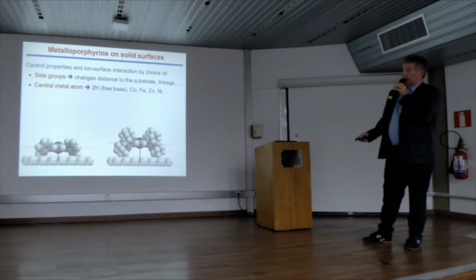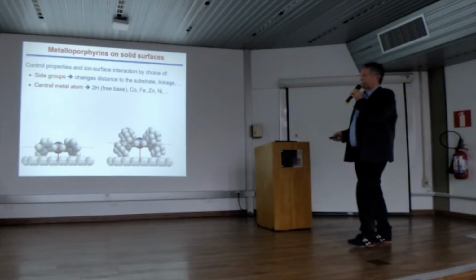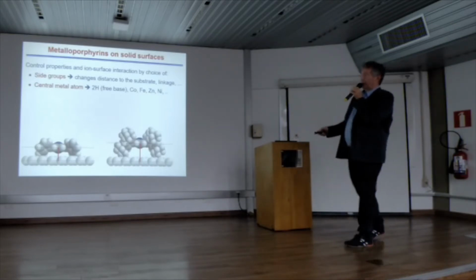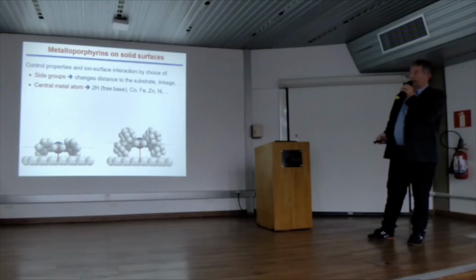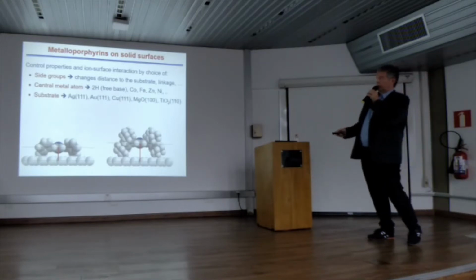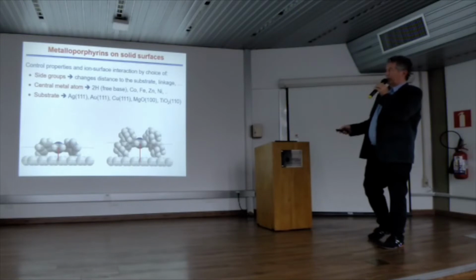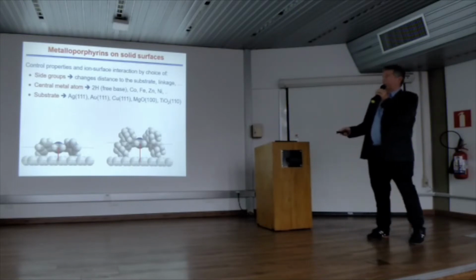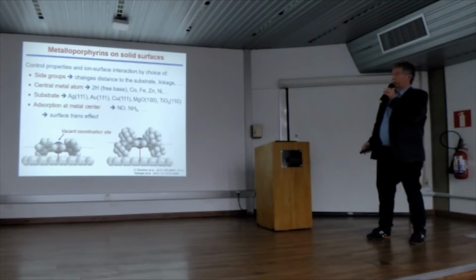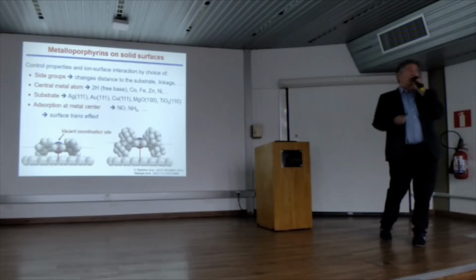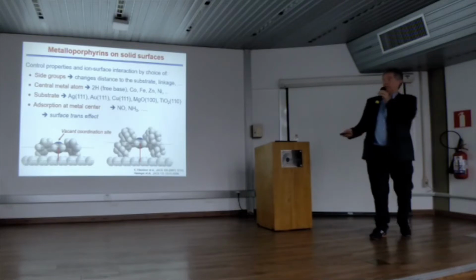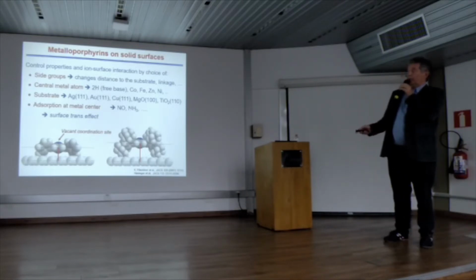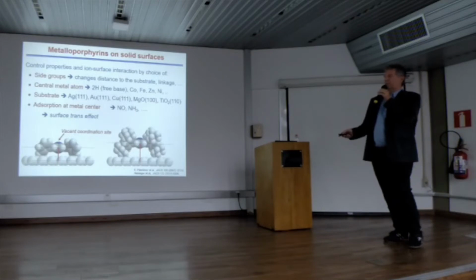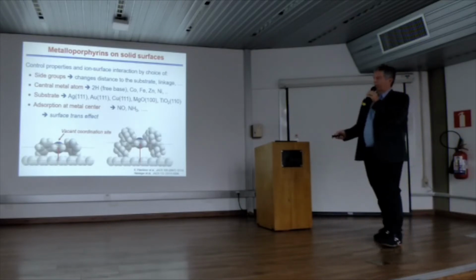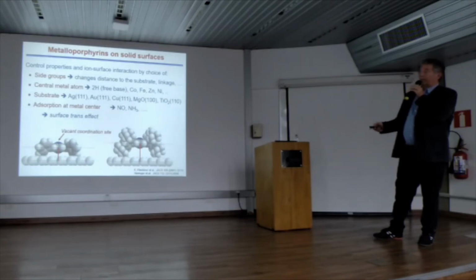The next thing you can do is change the metal atom in here. You can do 3D metals, you can do 4D metals, you can do no metal, this would be the free base porphyrin. And all that results in different properties. You can, of course, change the substrate. These are the substrates that we investigated: relatively inert metal surfaces and oxide surfaces. You can even adsorb NO or NH3 on the surface to mimic the effect of oxygen transport in blood, and then you get something which I don't address today, the surface trans effect. And that is our playground.